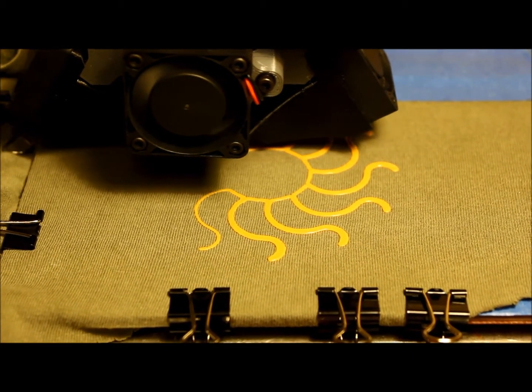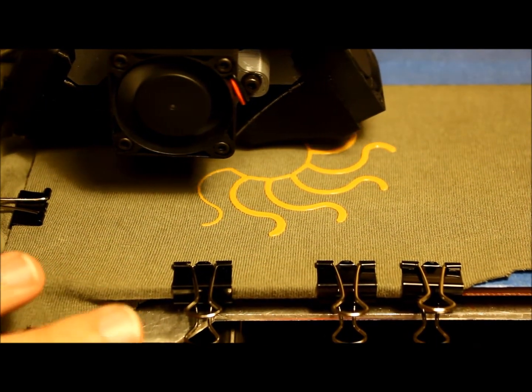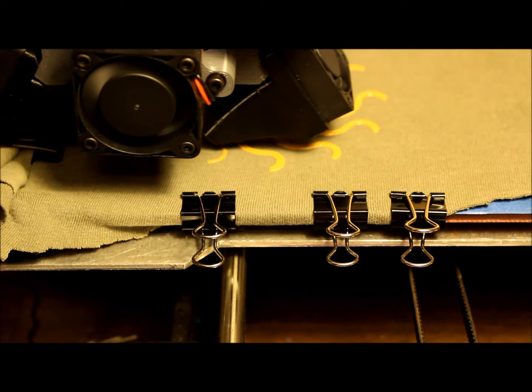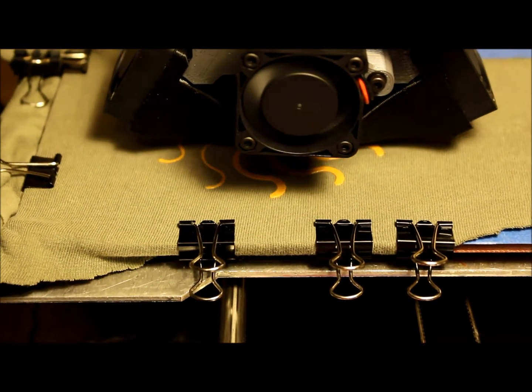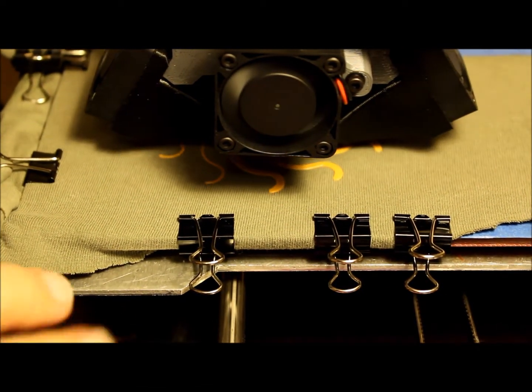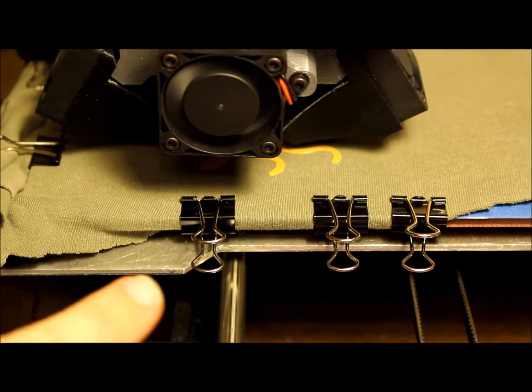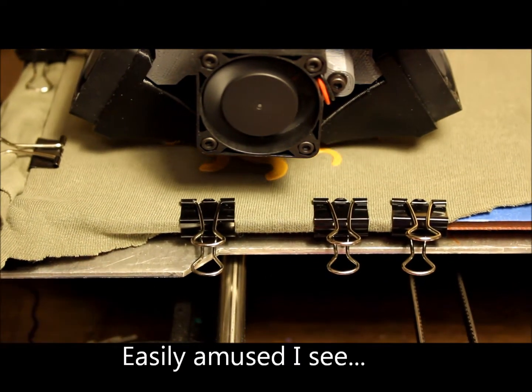This time I changed up the design a bit. I noticed during the earlier print the fabric shifted in the center, so I actually found some double-sided tape and put that down, which secures it really well. It's still printing in NinjaFlex and this already looks a lot better — a lot smoother. If you want to start by using a base layer first you'll have to play around with that, but the layer height on this is set to 0.9 millimeters, so it has some room for the filament to come out.